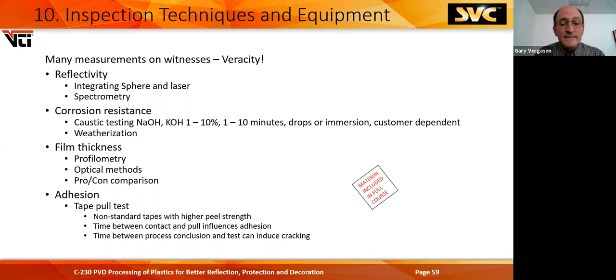Corrosion resistance, you can do caustic testing on the site, either with drop or immersion. NaOH or KOH, and we've seen percentages of anywhere from 1% to 10%, and anywhere from 1 to 10 minutes. We put a drop on there and it's got to make it through 10 minutes, you rinse it off and you can't see where it ate through the coating. Weatherization tests, going up and down in temperature and up and down in humidity. There are probably 50 different tests that the automotive industry uses on looking at PVD films.